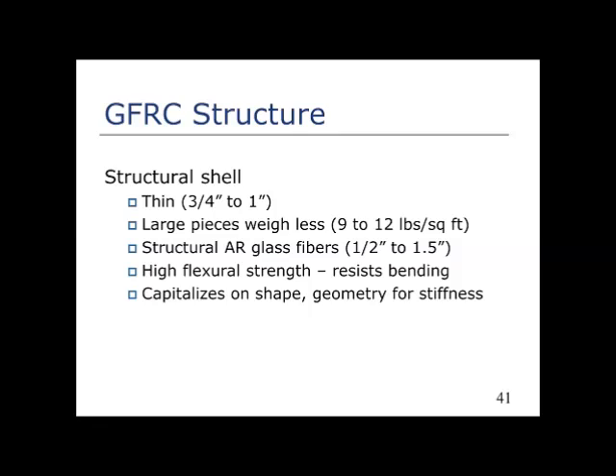If you had to spit out some numbers, for conventional concrete, forget the steel part, but just the concrete itself, your typical flexural strength is roughly around 600 or 700 psi. GFRC typically is around 2 to 3 times that, and when you incorporate scrim, it can be even more than that. So you have incredible flexural strengths, a lot of flexing that can occur, and it doesn't crack. Not only does it not fracture, but it doesn't even show a crack. So it's very beneficial from our standpoint of picky clients, high expectation clients, and people who don't tolerate cracks. That's not to say that you can't make it crack, but it's more resistant to it.